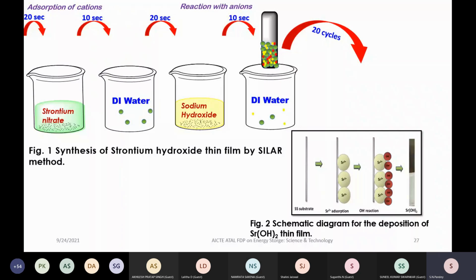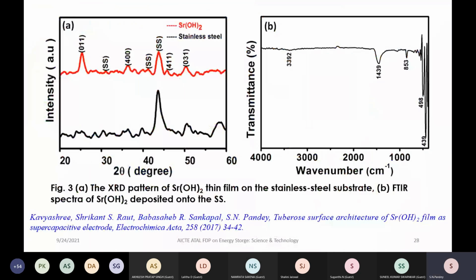So for that, we go for the XRD. So one can see here the XRD pattern of the strontium hydroxide thin film on the stainless steel substrate. So this is for the stainless steel. So one can see that peaks are here for the stainless steel, and here we are having this 011 phase and 400 and 411, 031. So one can get the information about which type of material we have developed.